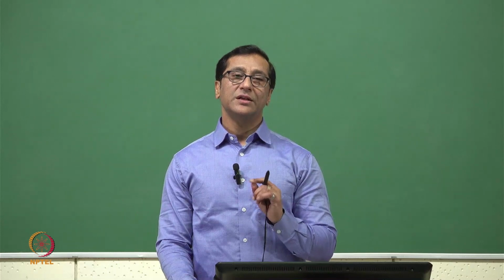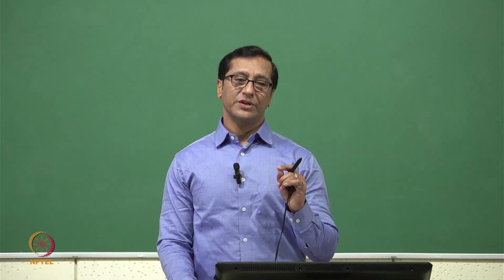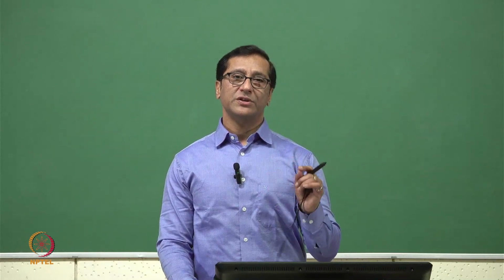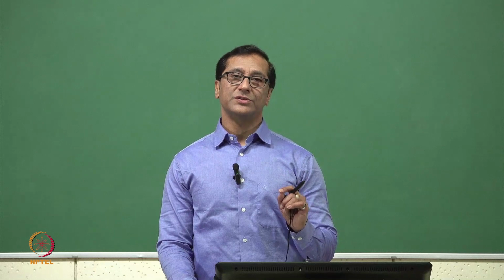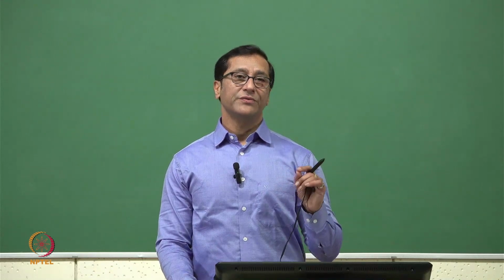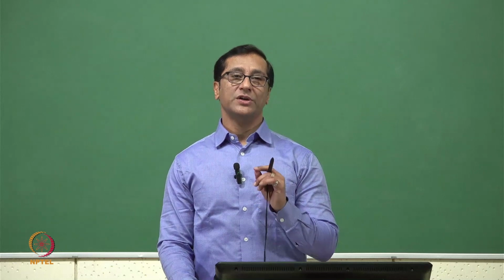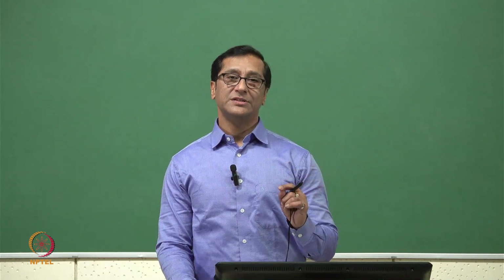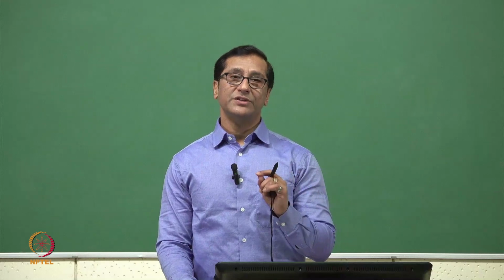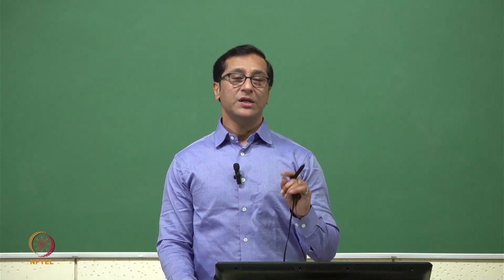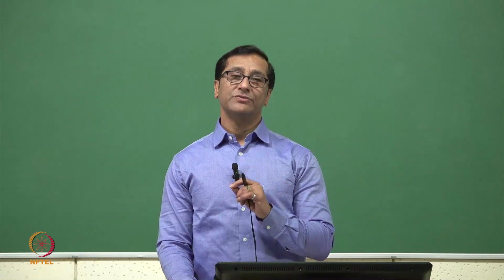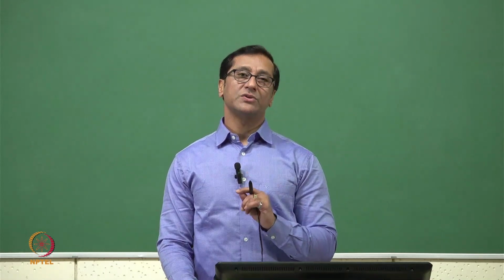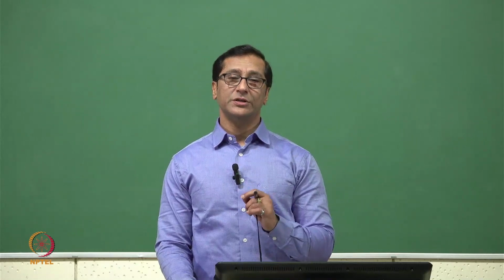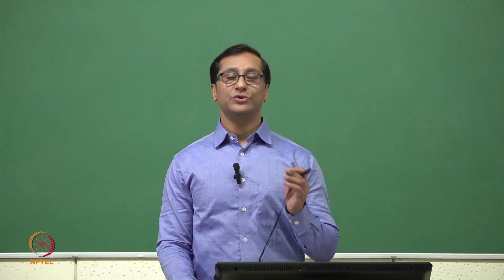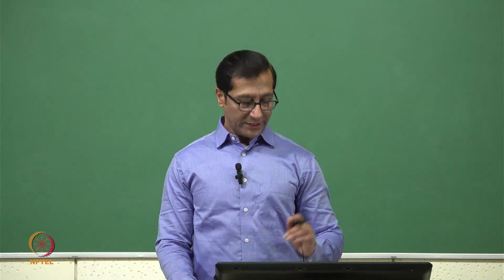even the wear experiment. That's why in one of the lectures I mentioned very clearly, many times people perform an experiment of 50 hours, and then after 50 hours they say okay, what is the effective wear constant or coefficient, but we do not know whether in those 50 hours 35 hours was running-in time, or 40 hours, or only 1 minute. If it is only 1 minute compared to the 50 hours, naturally we can neglect it, there's no issue. But if 35 hours was running-in time compared to the 50 hours, that is substantial. That means whatever wear constant they are quoting in their research publication or a book, it is useless, and we should not believe in that.